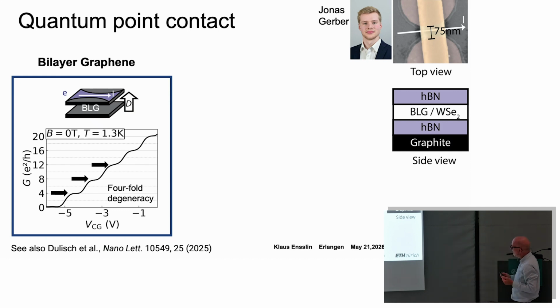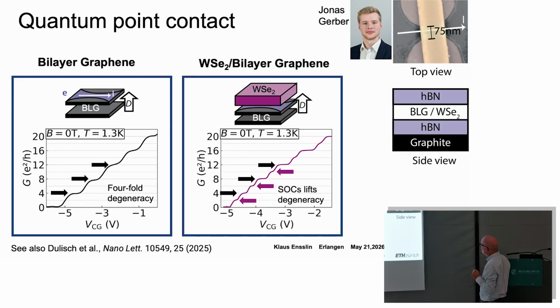So here I show you a quantum point contact. This is quantized conductance in a 1D channel, and this has been done in gallium arsenide 35 years ago. And you see that's graphene, nothing special here. You see quantized conductance in units of 4 e squared over h. That's what we expect: factor of 4, 2 for spin, 2 for valley. Now you make the same experiment, but you put a layer of tungsten diselenide on top. Now you see additional plateaus at 2, 6, 10, and so forth. So you have lifted this 4-fold degeneracy by the additional spin-orbit interaction.